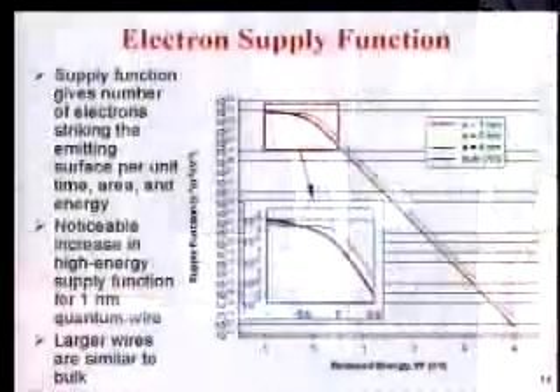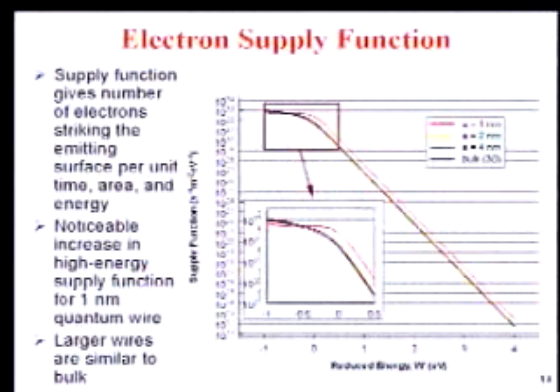And we see that for a one nanometer quantum wire, we actually are promoting energy in the direction that we want, more so than in the 2 and 4 nanometer cases. They look more like the bulk material. I should have mentioned that this energy, W, in the supply function represents the energy associated with momentum in the direction that I want to emit. So if my supply function is greater for a quantum wire at the same temperature, then I would expect more thermionic current. So as an engineer, you think, can I devise a device that might use this effect?